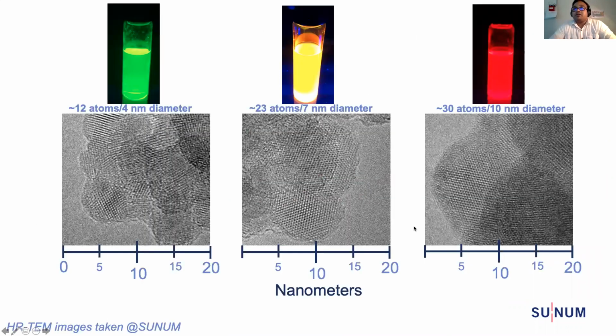After having this gradient synthesis, we could control the size and atoms in a nanocrystal. This is the single color for 4 nanometer diameter. You can see the size here, one of the sizes. And this is a little larger with 23 atoms, measuring about 7 nanometers in size. You have the largest one. This has 30 atoms, measuring about 10 nanometers in diameter.